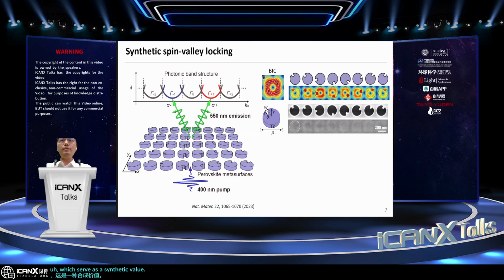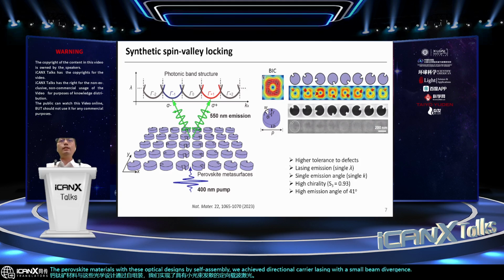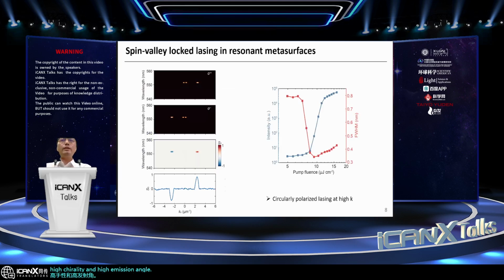This rotating lattice also imparts a geometric phase, directing photons with opposite circular polarizations to distinct valleys. After that, we monolithically integrate the perovskite materials with these optical designs by self-assembly. We achieve directional chiral lasing with a small beam divergence, high chirality, and high emission angle. Our experiment demonstrated that the lasing emission from each valley is both highly directional and purely circularly polarized.